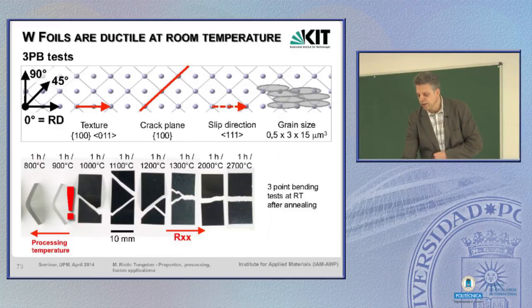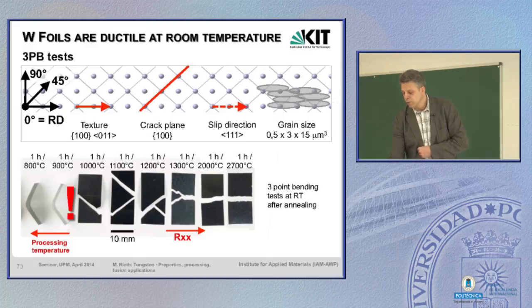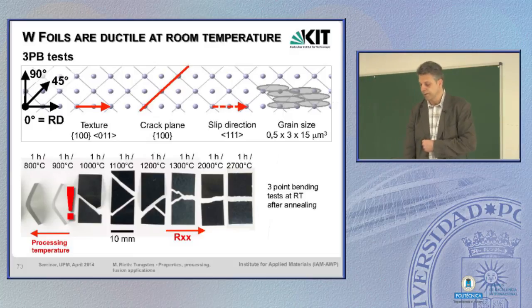It still can be bent, it shows plasticity, but starting from 1000 to about 1200 centigrades, you see cracks which are typically in 45 degrees to the rolling direction, and this is due to the texture in this direction and the cracking planes are usually in this direction, so something happens in the foil which makes them more brittle. And if you go higher with temperature, then recrystallization starts and another change of cracking starts inside the foil.